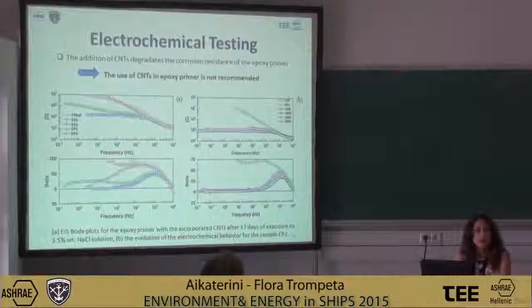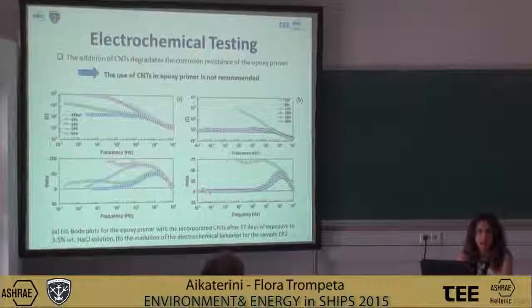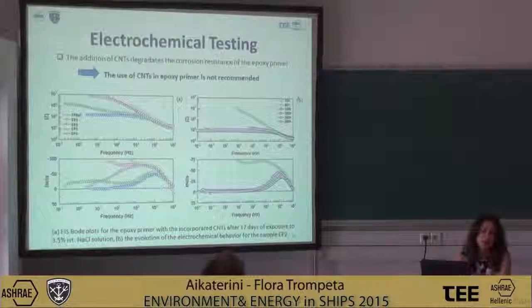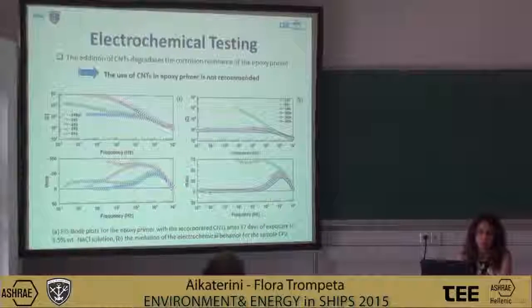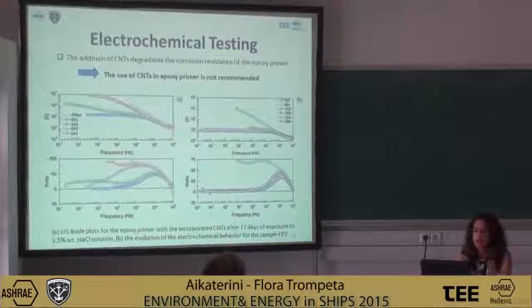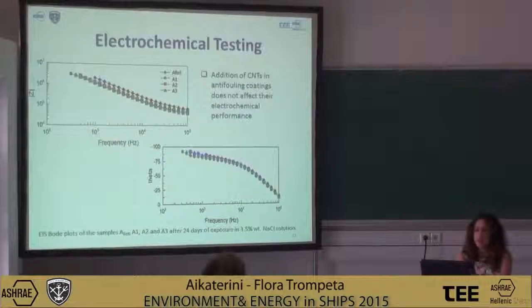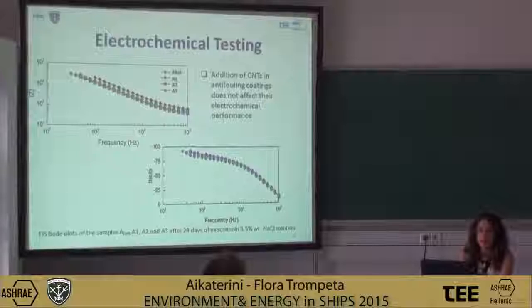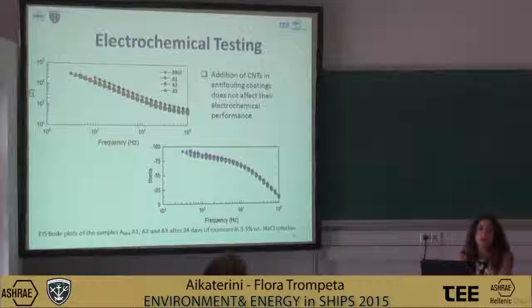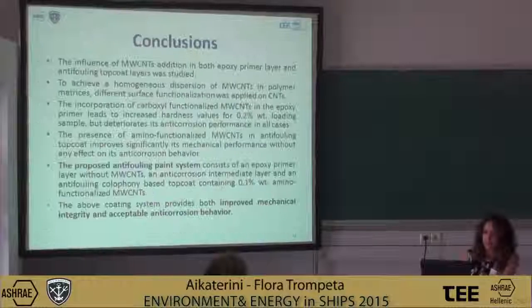So finally, it's not recommended to use the CNTs in the epoxy primer, while they may be giving some extra conductivity to the polymer matrix, enabling the corrosion phenomena to accelerate. Also, about the electrochemical performance of the antifouling coatings, we observed that the addition of CNTs didn't affect their electrochemical performance. From these plots, we can see that all coatings are performing like capacitors.